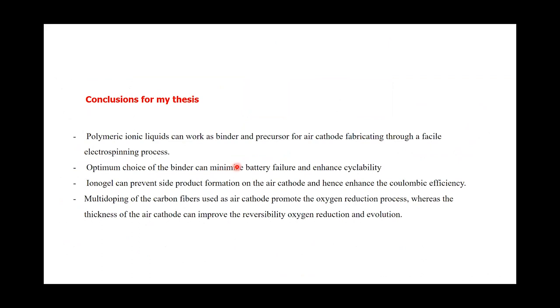So in my thesis, I show that the ionic liquid can work as the binder and precursor for air cathode fabrication during the electrospinning process. Selecting a binder is very important because it can minimize battery failure and enhance long cycling. Moreover, the ion gel can prevent byproduct formation on the air cathode and enhance the coulombic efficiency. Finally, multi-doping of the carbon fiber in the air cathode can promote the oxygen reduction process, whereas the thickness of the air cathode can improve reversibility, oxygen reduction, and evolution.